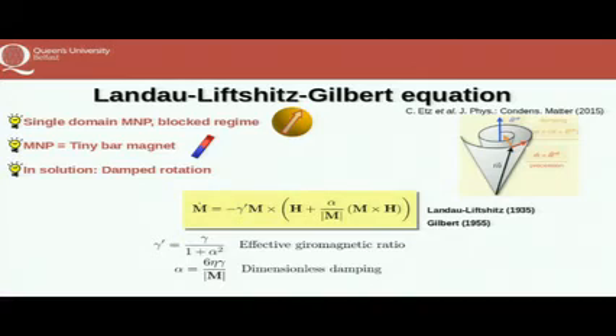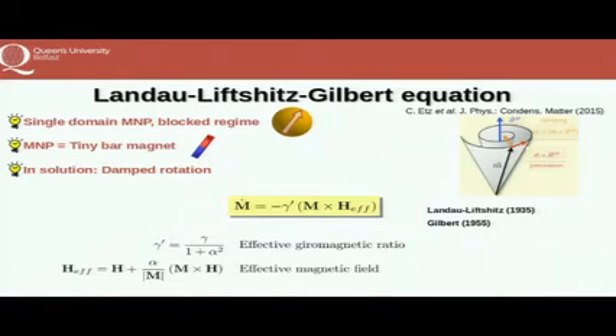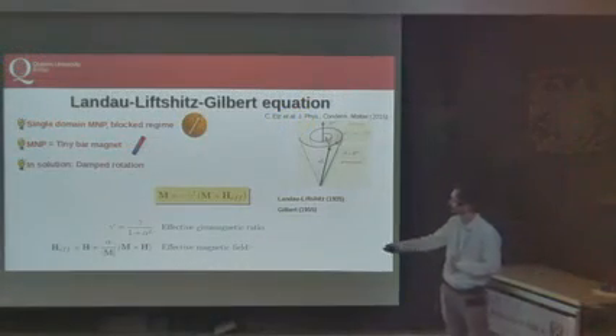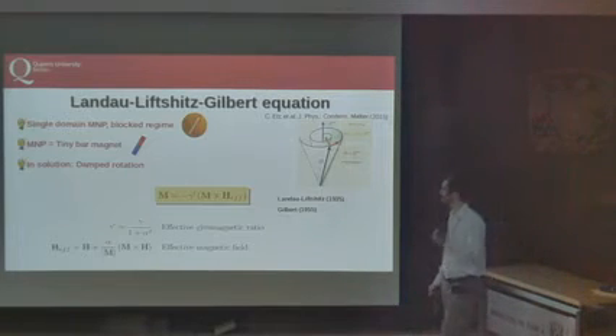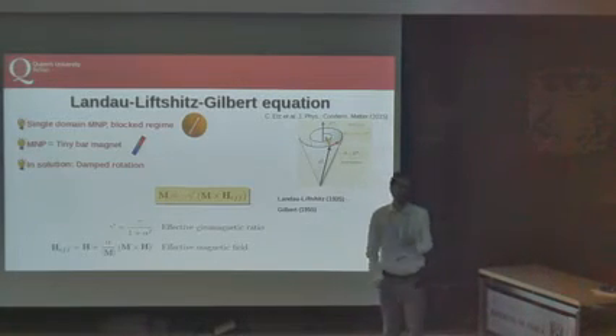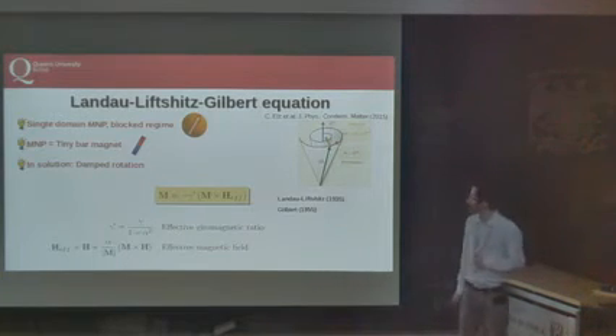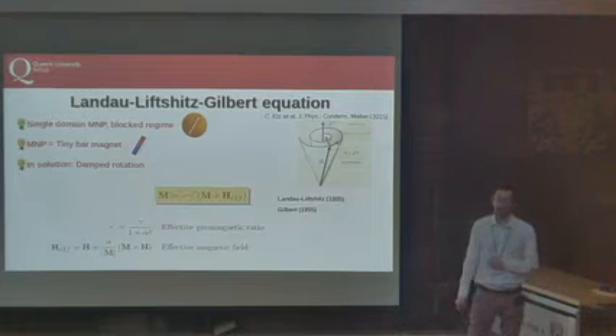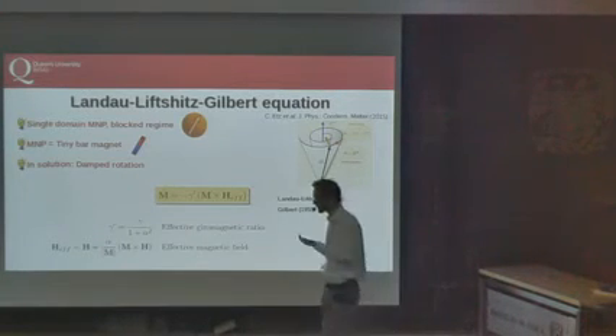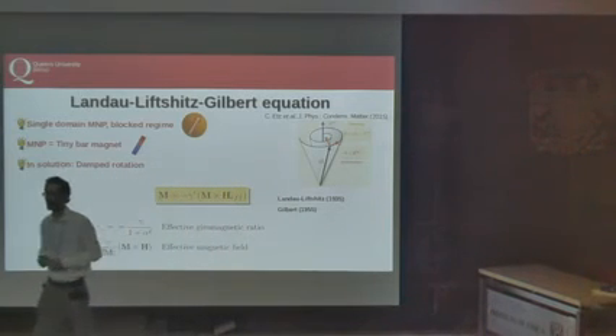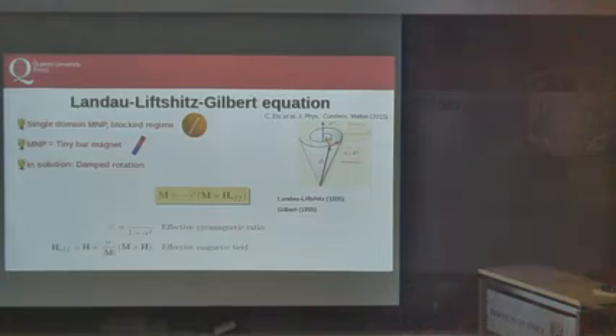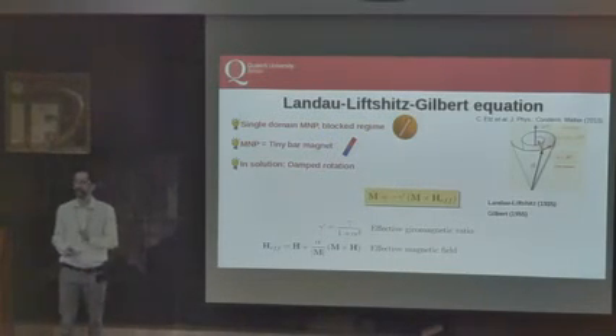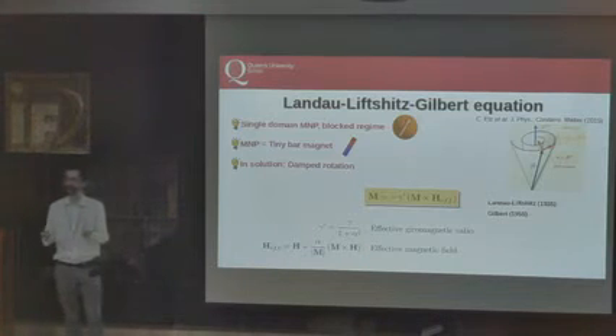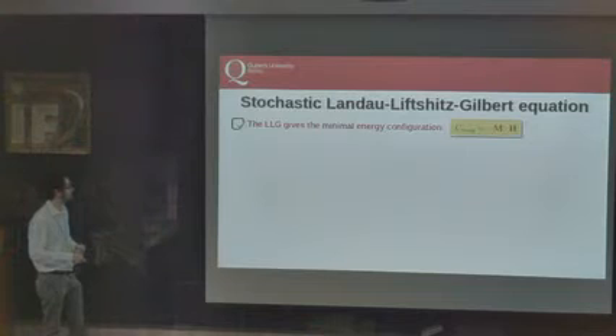And then if we compound everything in this round parentheses in a sort of effective field, which depends on the external fields, but also on this, let me say, drift field, if you want, our Landau-Lifshitz-Gilbert equation looks like the original Larmor equation. And this is a nice property of this spin dynamics, because we can use exactly the same good integrators that we can use for free rotation. We just have to take care of the redefinition of the magnetic field at each time step. And this is exactly what we do.